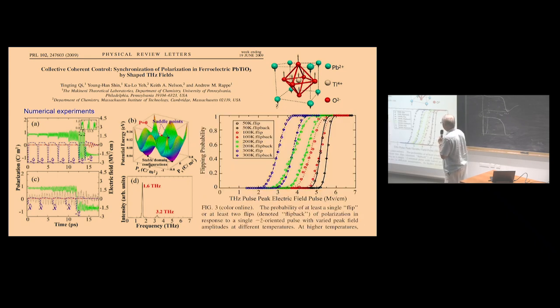But of course, better is to assume just one pump. They also calculated that if they pump it at low temperatures, 50 Kelvin, they need quite a huge electric field, 5 megavolts per centimeter. This is the electric field of the terahertz pulse, so this is quite huge. If you are at higher temperature, you can have it at only 3 megavolts per centimeter. And if you have two pulses, you can reduce this peak amplitude.